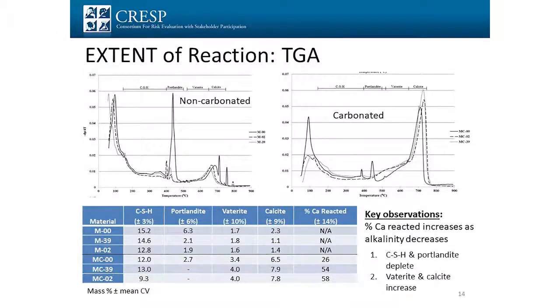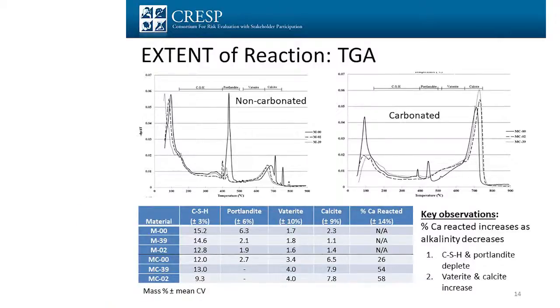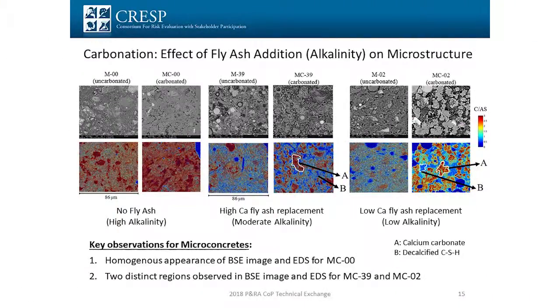If you carbonate the material, you'll see the CSH and the Portlandite will deplete, and the vaterite and the calcite, and vaterite is an analog for calcite, will increase, which makes sense because you're carbonating the material. So this is what you expect to see in something like a concrete, and this is thermogravimetric analysis. You can see some pretty profound effects from the carbonation. People often talk about pore structure refinement when you carbonate something like a concrete, and you can actually see that as well.